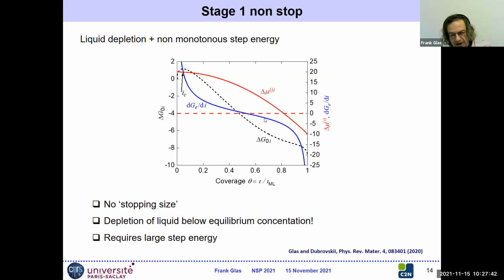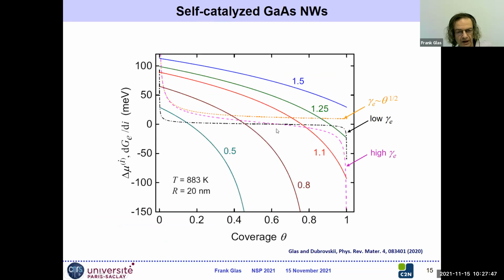But for this to happen, it requires a relatively large step energy, of course, for the effect of the step to be important. So before, there were schematic curves. Now let us see what it means in the case of self-catalyzed growth. Here, what I've plotted, the dashed curves are the step energy. The orange one is the energy in the bulk case, the square root energy, so the derivative is the inverse of the square root. And the other dashed curves are in the case of non-monotonous step energy.